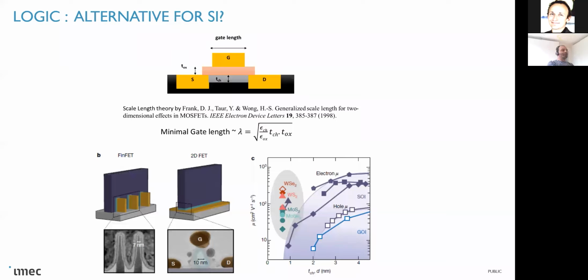But finally, the holy grail of 2D material integration is the replacement of silicon for CMOS applications. This is a very challenging one, but why are 2D materials so interesting? If you want to scale your gate length to very short lengths, you need to scale the body of your semiconductor too. And what you see here is that if you do that for silicon or germanium, you see a dramatic drop if you thin down that body thickness. 2D materials have the promise that even for a monolayer, they could still have relatively high mobilities, what you need for your drive current. And this is the very attractive thing there.